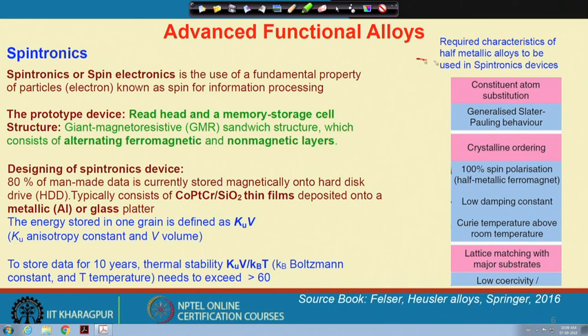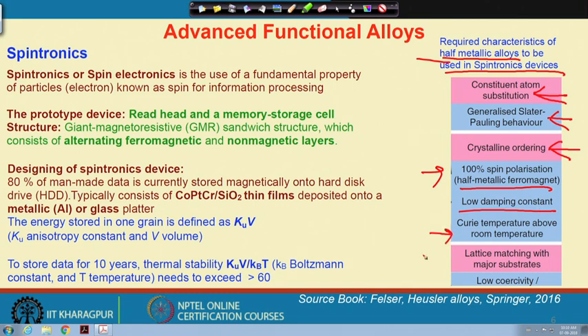So, there are some basic requirements for spintronics, like half metallic alloys to be used for spintronics devices, where we need some constituent atom substitution, which we call half metallic elements, and so on, and we need a generalized Slater-Pauling behavior, which we have already discussed during the magnetic material discussion. We also need some crystalline ordering, so far L21 structures and so on we have discussed. We also need 100% spin polarization, a typical feature of Heusler type compounds or half metallic ferromagnetic materials. Also we need a very low damping constant, and a Curie temperature above room temperature,